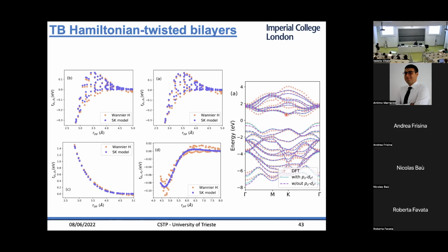But what kind of orbitals do you start with? You can start to use atomic orbitals, but then you use a larger basis. Yes, a larger basis, and the risk is overfitting. The basis set should be larger. No, we haven't tried it. We tried with 6 nearest neighbors, and we actually managed to capture these pockets here in the band structure, which we completely missed with the third nearest neighbors.